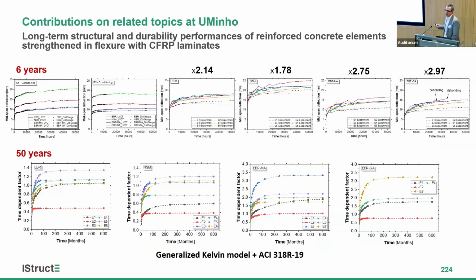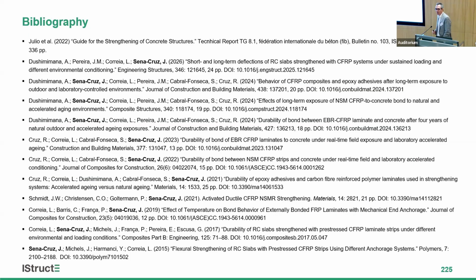Finally, to show you also a structural level, because we have slabs that are loaded for more than 6 years. So these are results of displacements over the 6 years. These values here indicate the comparison with the displacement at short term or instantaneous deflection. But the most important one was we are trying to predict what will happen in 50 years for these non-pre-stressed EBR and NSM, as well as pre-stressed systems, because this is important while we design. And here, using some analytical models, for instance, based in this case on the generalized Kelvin model, we are proposing some factors, I could say, almost, not exactly creep factors, but close, that give you a possible prediction about this. Okay, so here I have all the literature that supported this presentation.